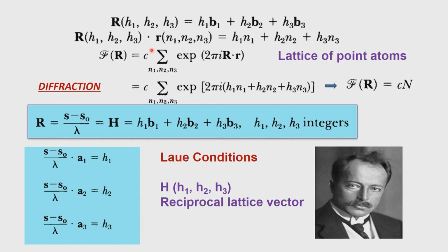We showed some points which come out from the scattering experiment. Whenever scattering experiments are done on crystalline objects, if it is a 3-dimensional crystal, we will get spots, and these spots represent the values of H1, H2, H3, that is where the spot will occur with respect to the reciprocal lattice. So we can find the coordinates of the reciprocal lattice point in terms of H1, H2, H3, which can be replaced later by HKL, the so-called Miller indices. This is where Laue completed this work, and he got the Nobel Prize in 1914, I think.